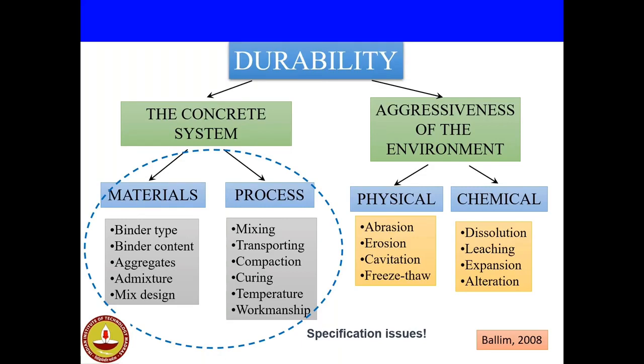For example, if you use the concrete for a pavement, abrasion might be an issue, shrinkage might be an issue. If the same kind of concrete is used for the construction of a dam, there, in addition to abrasion, you might have cavitation. In that case, we are not using reinforcement, right? So in that case, we don't have to bother about the chloride-induced corrosion or carbonation-induced corrosion of the rebar. And if it is laid in a sulfate-laden environment, in a soil which is rich in sulfate, you might face sulfate attack. So depending upon the type of exposure or the aggressiveness of the environment, your deterioration mechanism may change.